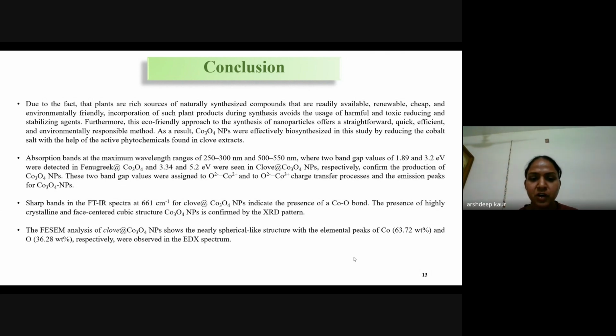of Co3O4 nanoparticles. Sharp bands in the FTIR spectra for clove extract-mediated Co3O4 nanoparticles indicate the presence of cobalt and oxygen bonds. The presence of highly crystalline, face-centered cubic structure Co3O4 nanoparticles is confirmed by the XRD pattern. The FESEM analysis shows the nearly spherical structure with the element peaks of 63% cobalt and 36.28% oxygen, which were observed in the EDS spectrum.